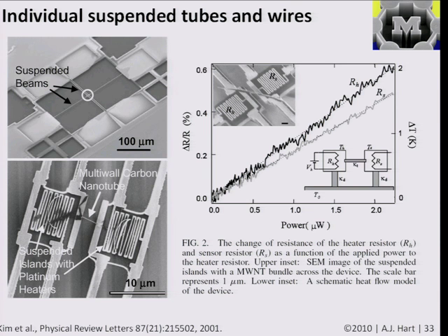And when you design an experiment like this, you have to be very careful that you're not losing heat to other places that would kind of distort your measurements. So these are designed to be very thin and not conduct heat, and everything's done in a vacuum and shielded from radiation and so on. But that's the idea. So you can map out the conductivity of this structure.